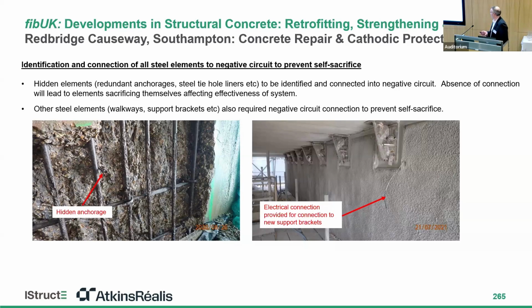And then on the other side, there's a couple of additional brackets we had to add on. Again, because they're going into the concrete, they would be affected by the CP. We had to stop the mesh short of the bracket, which is what the channel around the bracket is showing. And then the black cable hanging out is ready for a negative connection. So all the brackets are linked together with a continuity bar and then connected back to the system negative. So again, nothing will corrode within the system.